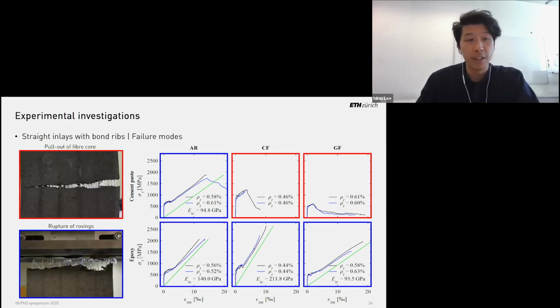There were generally 2 different types of failure. Most of the specimens exhibited a complete rupture of rovings and brittle failure without prior notice, the ones with the blue frame. However, carbon and glass fiber rovings coated with cement paste failed shortly after cracking, and especially the glass fiber rovings here, they showed a distinct softening behavior, which comes actually from a pull-out mechanism where only the outer fiber breaks and the fiber core is pulled out.